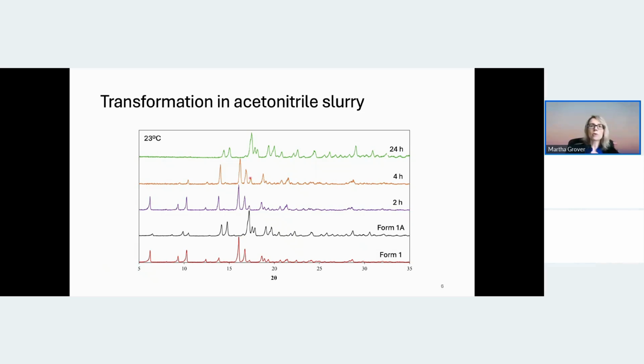And after 4 hours, not so much change also, but after 24 hours in the acetonitrile at 23 degrees C, we now have an XRD pattern that looks very much like Form 1A. So we were able to see that Form 1 did dehydrate and form a similar structure in the acetonitrile slurry as it did in a vacuum. It makes sense. The acetonitrile doesn't really have water in it, so there would be a driving force, presumably, for the water to come out of the crystal. But it does take some time at 23 degrees C. Even after 4 hours, it really had not dehydrated.